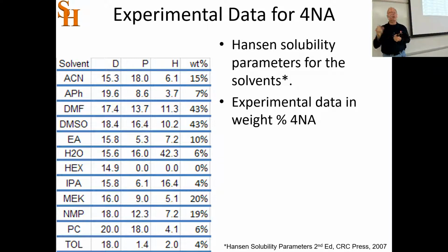It didn't really work. We tried to suspend carbon black in these different solvents, and it just stayed at the bottom in all of them. So we couldn't really get a good handle on which one would be a good solvent for suspending carbon black. Apparently you need some other additive that will coat the carbon black and carry it into solution, either as a colloid or something like that. Sometimes you have an idea, you go try it, it doesn't work, and then you do some more research and try something else. I made it look easy because this worked, but you don't see the times when things didn't work.